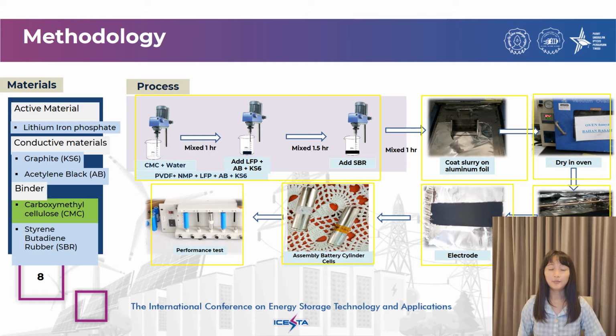The slurry is then placed on aluminum sheets using a vacuum coating machine, coated to a thickness of 150 to 200 micron. The sheet is then dried in the vacuum oven, then removed from the oven to coat the other side with the same slurry. This will compress the electrode. Then store the compressed electrode in the vacuum oven to wait for assembly of the battery cell and test. Next is assembly of the battery cylinder cell and finally a test with the battery testing machine.